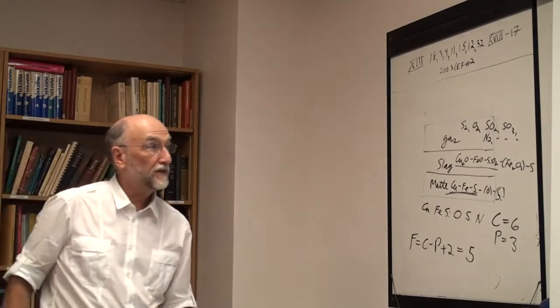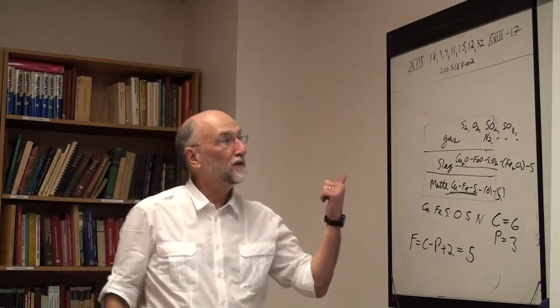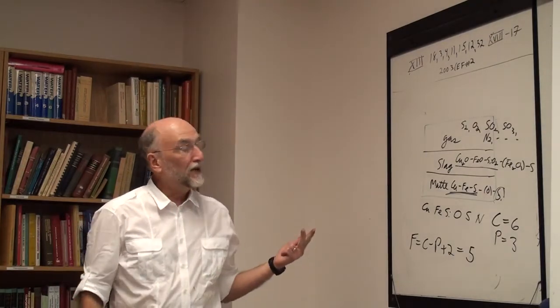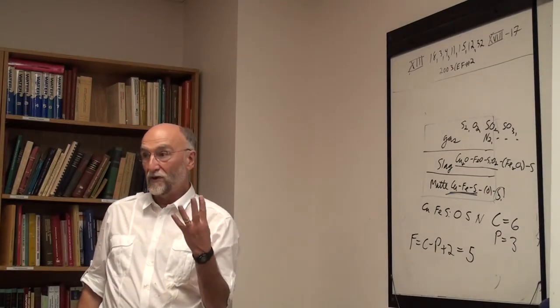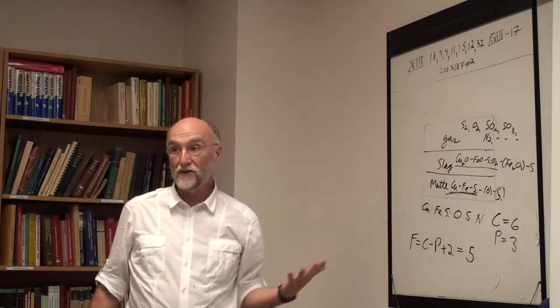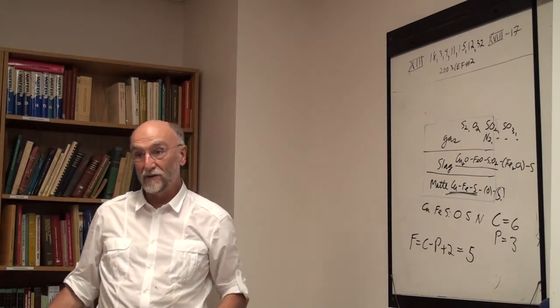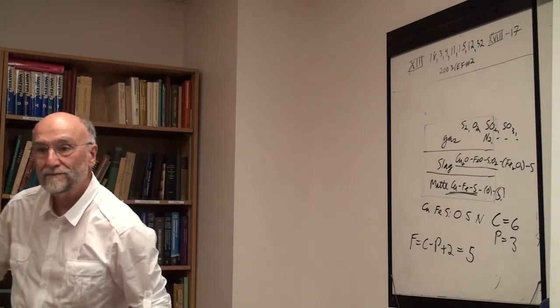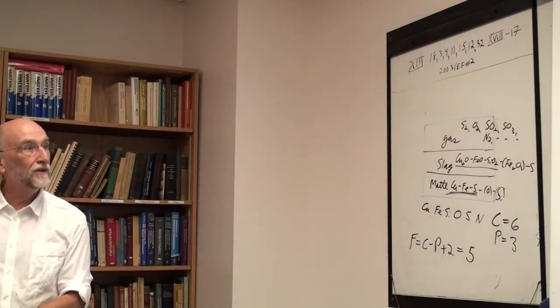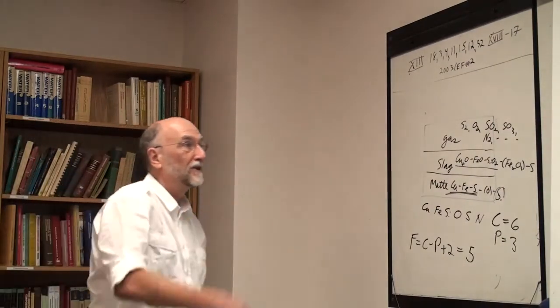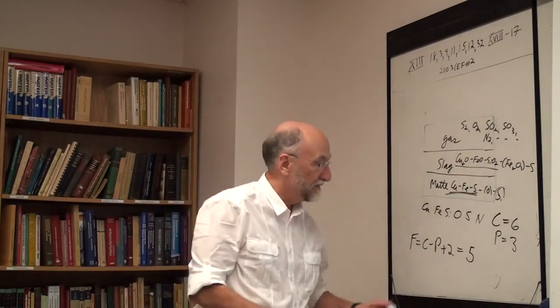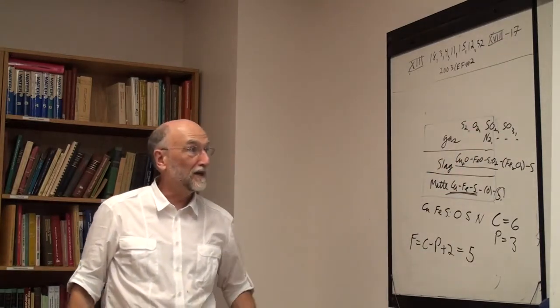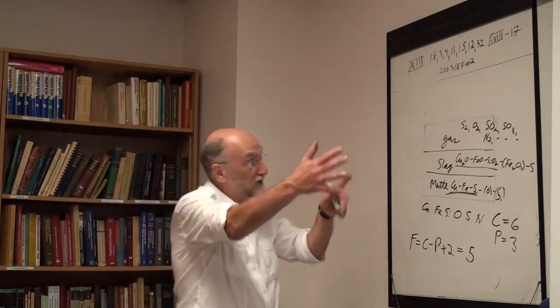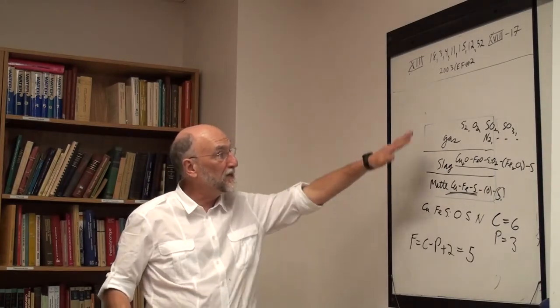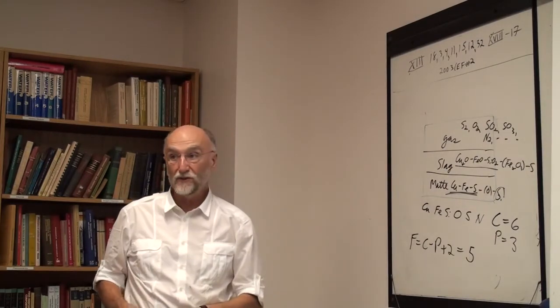So what I fixed is the temperature, 1; total pressure, 2; PSO2, 3; PO2, 4; content of sulfur in the slag, 5. That's it, 0. Everything else is now going to be fixed. So yes, the answer is yes. Is he right? Yes, he's right. If you had another system with exactly those 5 variables the same, you would have the same slag and matte composition in the two cases.